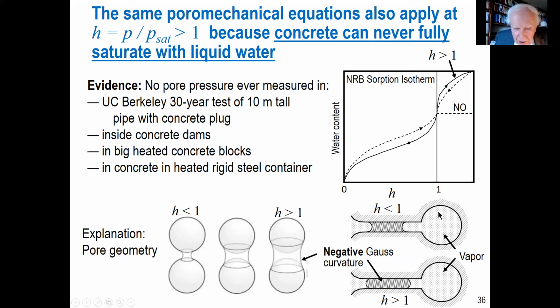For example, if you have a pore which contains vapor and humidity is less than 1, you have equilibrium with positive meniscus here. This is liquid as pore, but you can have also equilibrium at big pressure here of water or steam. And then you have a negative Gaussian curvature, which is also equilibrium. And to fill this takes a long time, diffusion, and eventually to smaller and smaller pores, and probably it never happens in practice. Another example, there are many examples. Two spheres at low humidity, there is a hyperbolic surface with positive and negative curvature. At 1, they are equal, Gaussian curvature is 0, and at positive curvature it is negative, but still you have vapor around it. And there are many other situations like that. So concrete can never be fully saturated, and this was omitted in calculations at first.